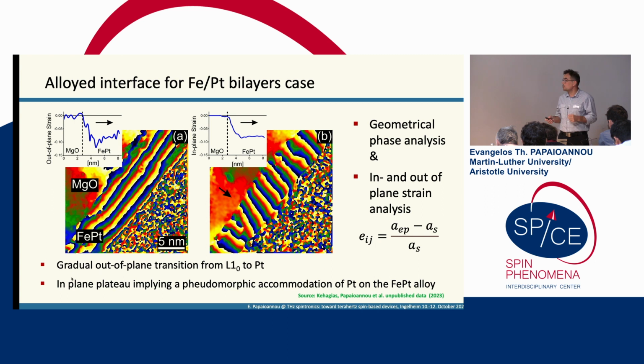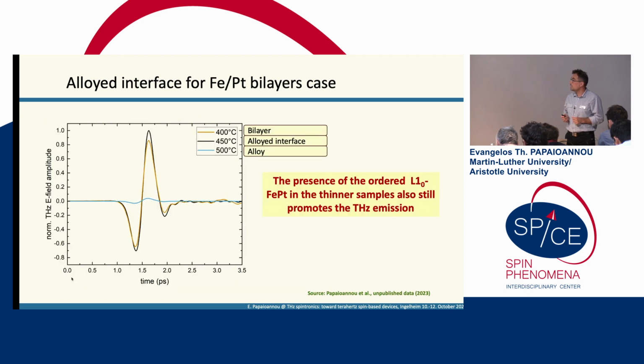Does this structure give us a good terahertz signal? So in principle, yes. So again, we see the same. So the highest curve is the sample which I call with this alloyed interface, with the structural data I saw before, and it's above the bilayer. And if you try to go high to make the alloy in the volume, then you again decrease the signal. So the conclusion here is that the ordered L10 phase as an interface even keeps the highest terahertz signal, even for the thinner samples.